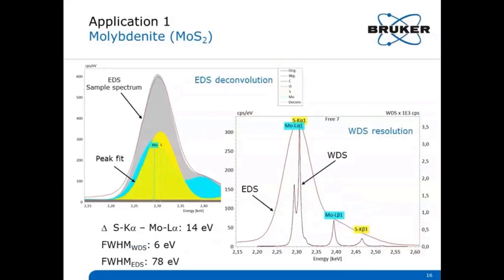WDS instead resolves X-ray peaks. With a 13 times better resolution than the best EDS, QUANTAX WDS can separate, means resolve, the molybdenum and sulfur peaks from each other. The diagram on the lower right shows the WDS spectrum, which is actually an energy range scan, in comparison with the respective EDS spectrum section.